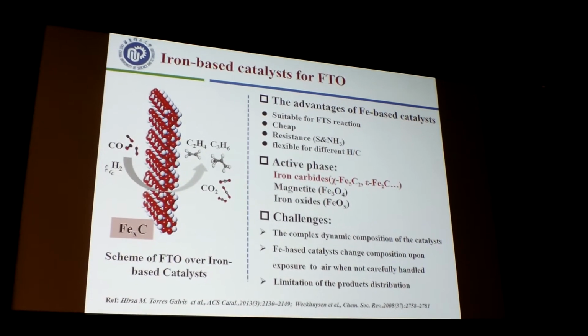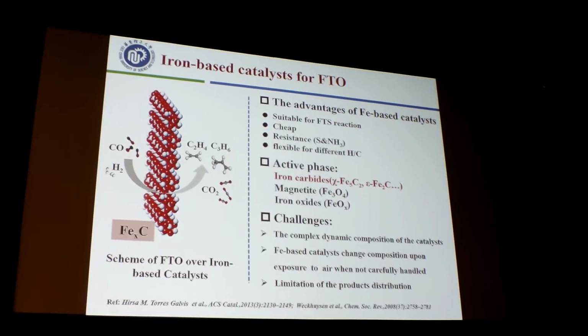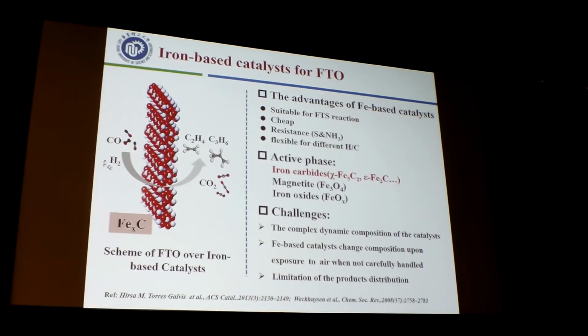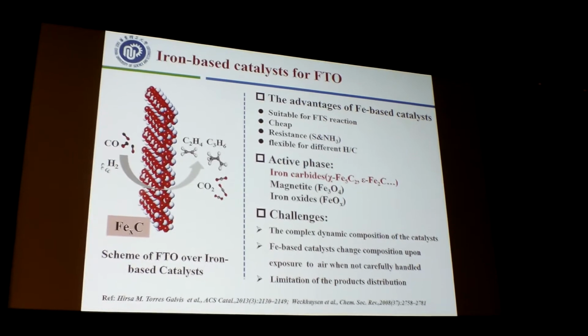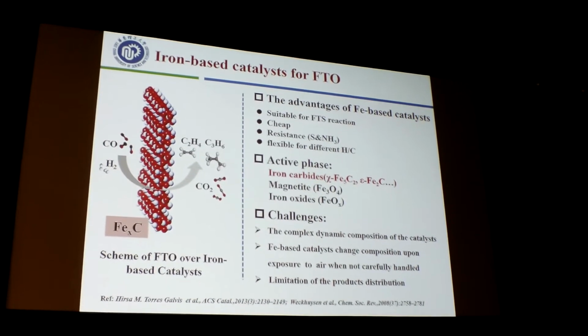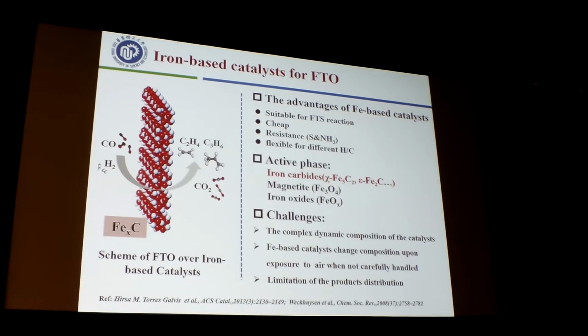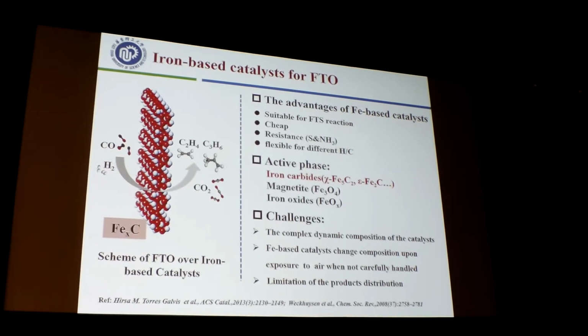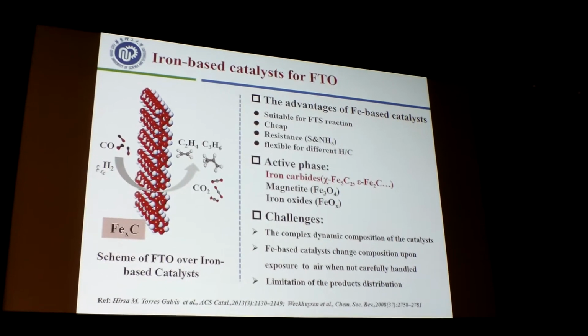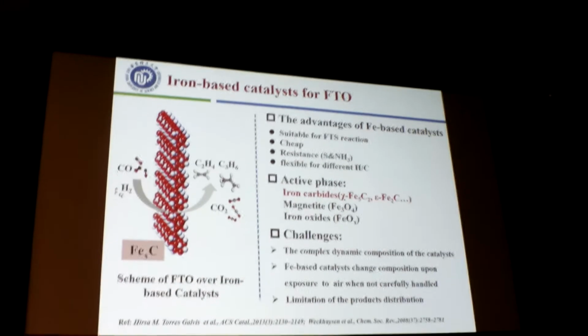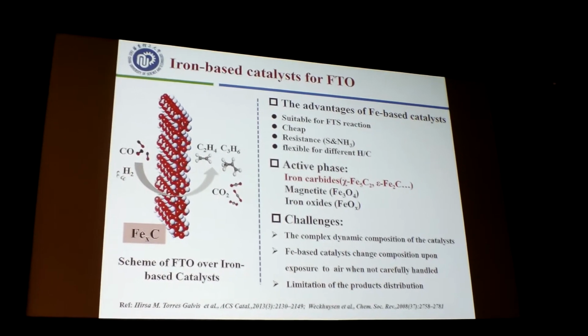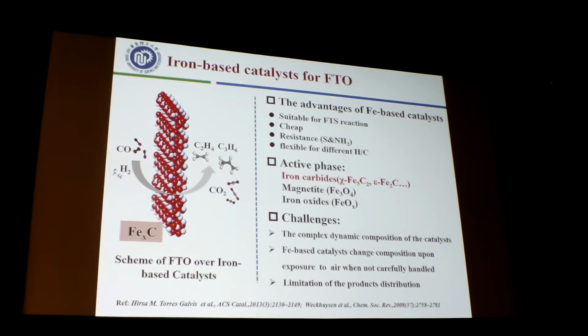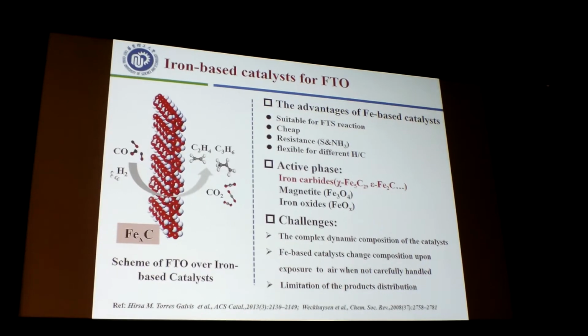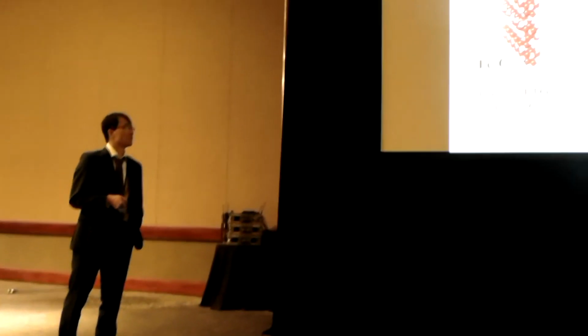The active metals that drive this process need a strong capability to dissociate carbon monoxide. The commonly known active metals for such a process are iron, cobalt, and ruthenium. Recently, iron-based catalysts have been extensively researched because of their low cost and high resistance to poisoning, and because iron is active for the water gas shift reaction, so it is more flexible to different hydrogen to carbon ratios.